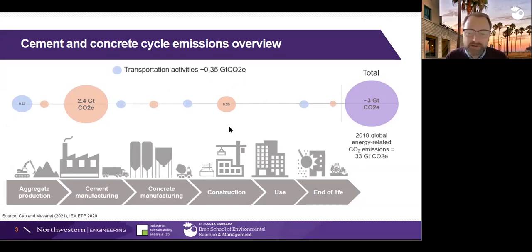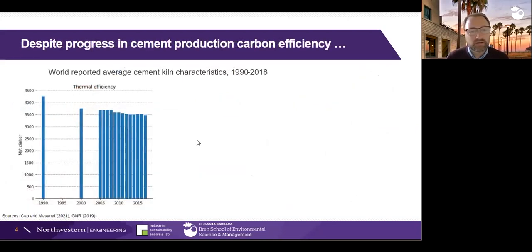And just to put that into perspective, that is not quite 10%, but almost 10%, 9 to 10% of global energy-related CO2 emissions. So a single material system accounts for nearly 10% of all those emissions. So it's no surprise that we now have raised climate ambitions with the Paris Agreement. The ideal goal is to keep global warming to 1.5 degrees, or well below 2 at least. It's clear that we can't get to net zero emissions without decarbonizing the cement and concrete cycle.